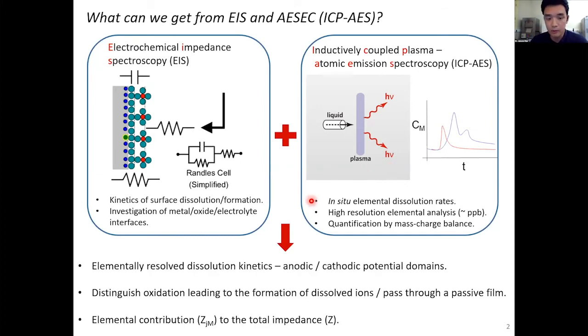So this coupling will allow us to have elemental-resolved dissolution kinetics, whether in the anodic or cathodic potential domains. It will also allow us to distinguish whether oxidation leads directly from the surface to forming the cations, or the dissolution occurs through a passive film formed on the surface. And it can also give the impedance contribution of each element, so that we can compare with the total impedance measured by conventional electrochemistry.